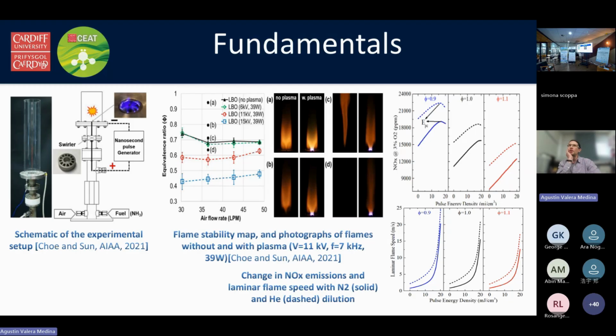And it was very interesting because once they started using it, what they found out was that the stability improved, the flame got better, and also the emissions profiles in terms of nitrogen oxides that we tend to have from ammonia combustion went down drastically. So as part of that program, we started working with our partners in Birmingham and also Oxford, and delivering some analysis via numerical modeling.